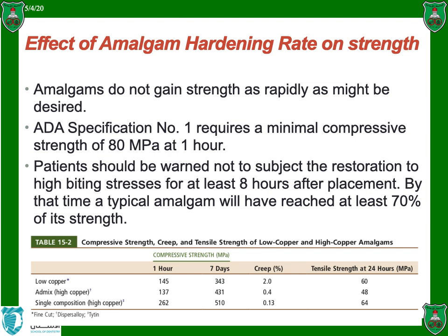And you can see the compressive strength after 1 hour and 7 days. You can see that after 1 hour, most of them or all of them are above 80 MPa that has been defined by the ADA specification. So they have a clinically acceptable strength after 1 hour.